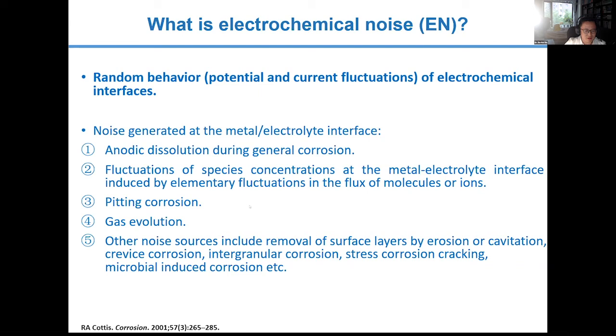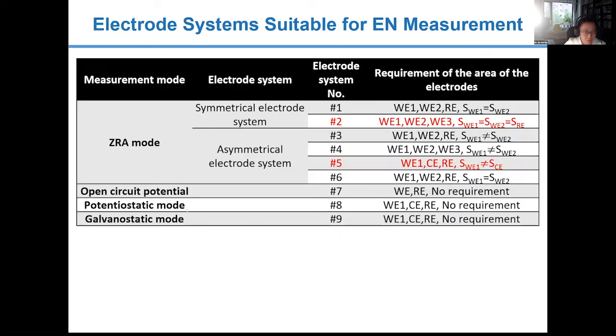Electrochemical noise is a general term given to fluctuations in the potential and current generated spontaneously by corrosion process. Noise sources at the metal electrolyte interface can be anodic dissolution, during pitting corrosion, localized corrosion, and fluctuations of species concentrations at the metal electrolyte interface. As summarized in this table, there are nine measurement modes that can be used in measurement. ZRA mode is the most frequently used in field corrosion monitoring because it can measure potential noise and current noise at the same time.